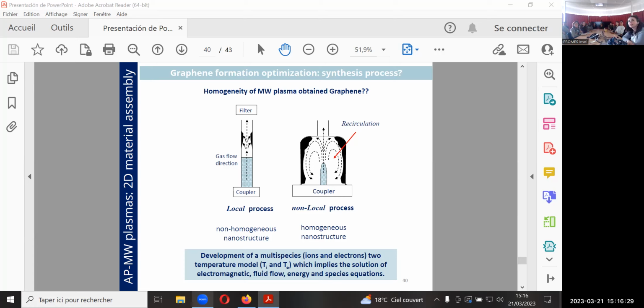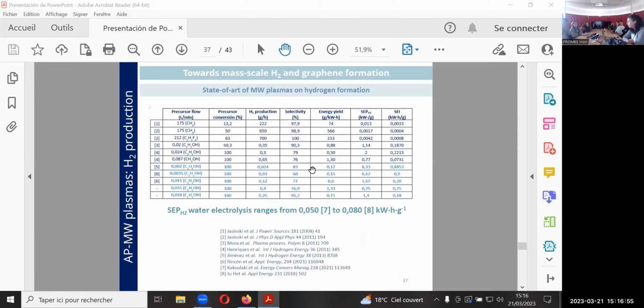Any ideas of options to try to increase the yield efficiency? No, to increase the yield efficiency for the hydrogen production. Yes, you showed tables with comparisons between different yield efficiencies. Right now, we are trying to work with the TIAGO torch, which allows for introducing a higher amount of ethanol. We are limited in terms of the amount of ethanol that we can introduce, but not because of the plasma, it's because of the equipment.